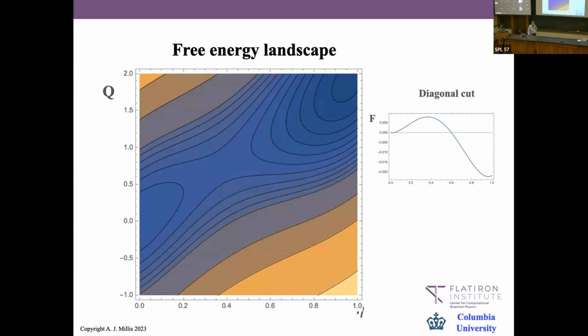Is there a way to directly relate it to the order parameter? No, because it's a first order transition. The direct thing you can do is see that the paramagnetic minimum is locally stable, but you knew that already because it was a first order transition. Indirectly, these experiments on strained films are telling you something, but exactly what, I think, requires an analysis sort of like this to really know.